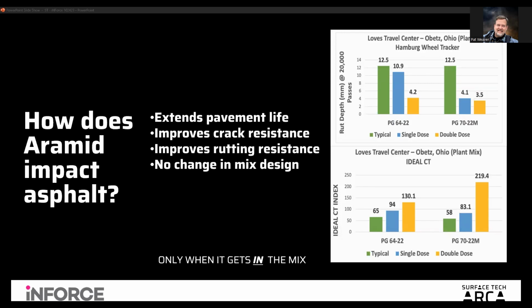That's what aramid does when it gets into the mix properly and is well mixed, and it creates that three-dimensional array within that aggregate and binder structure. If you look at it proportionally, you can see up to a 4 times improvement in crack resistance from this one project, this one lab test, and up to a 3 times reduction in rutting with that same mix design when it comes to a wheel rut test. So those are some very unique, amazing results from a laboratory perspective.